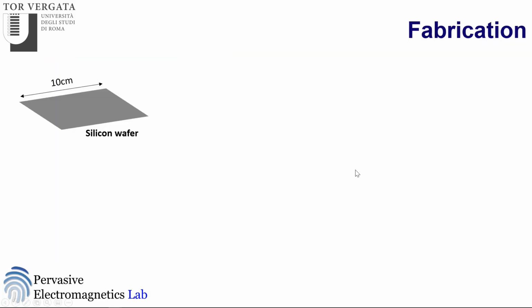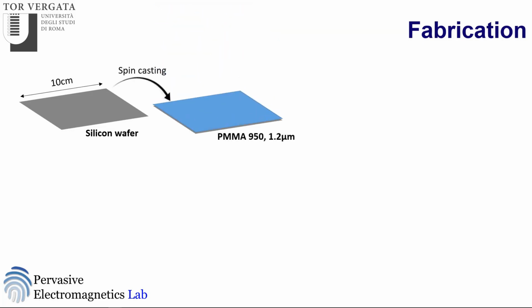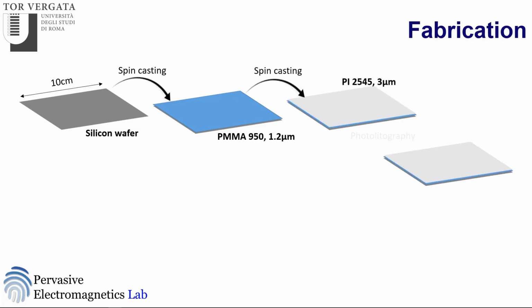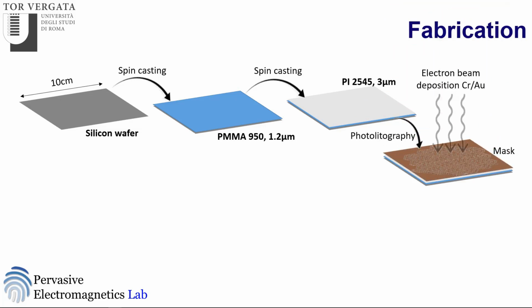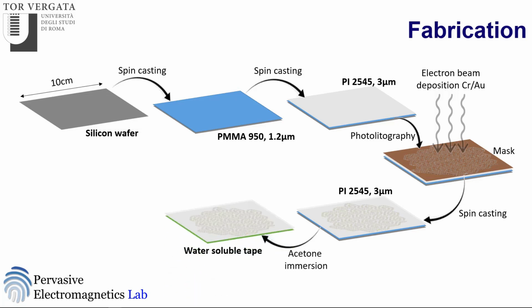The fabrication of the space filling curve began with the spin casting of PMMA, a sacrificial layer, on a 10 cm silicon wafer, followed by the spin casting of a layer of polyimide. Then, by electron beam deposition and photolithography, the gold traces have been patterned as a thin film with the desired geometry. A second layer of polyimide, spin casted and cured, has been added to completely encapsulate the space filling curve. Afterwards, the sample has been immersed in acetone for 40 minutes to remove the PMMA, and then the remaining part has been transferred to a cellulose-based water-soluble tape. Finally, using water to dissolve the tape, the device has been moved over the previously treated and prepared Ecoflex substrate.